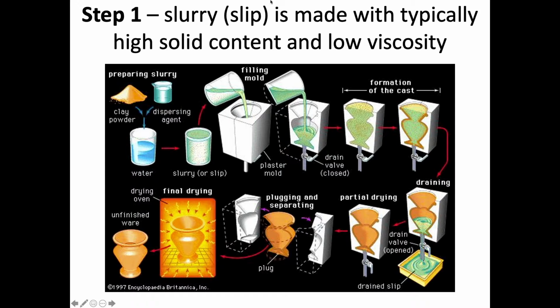We need to prepare it, and so this is where our additives come in. So we may actually have to add some type of dispersing agent along with the liquid, such that our powder is evenly dispersed and doesn't fall to the bottom. In the previous section on powder processing and characterization, you'll remember that we talked about sedimentation, and we can use that to determine particle size. Well, we don't want that to happen here. We want the powder to remain in the liquid until the liquid's been removed, and that's the part we want to maintain.